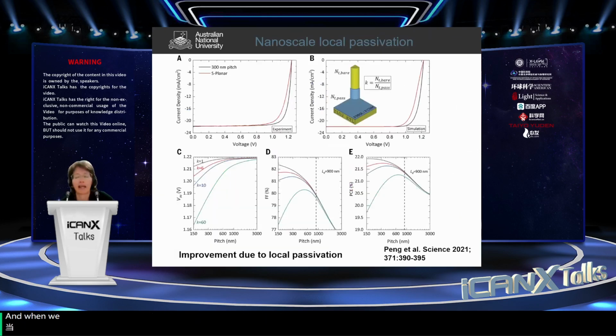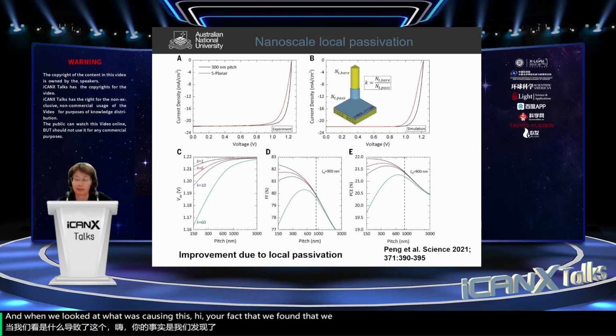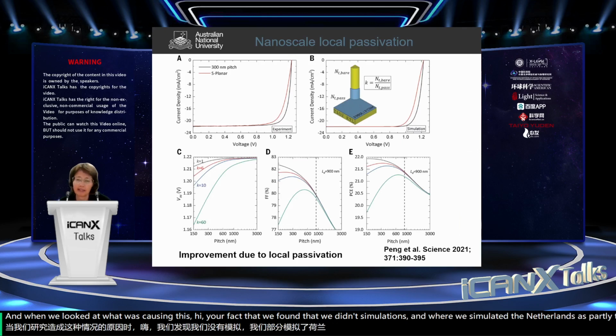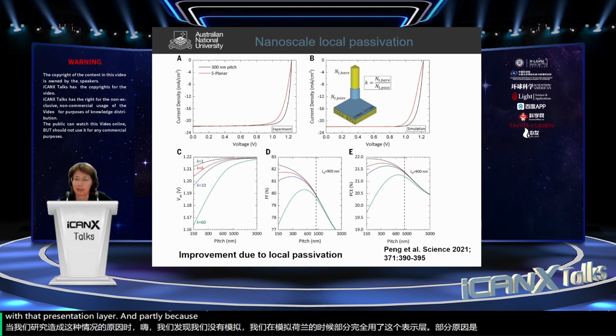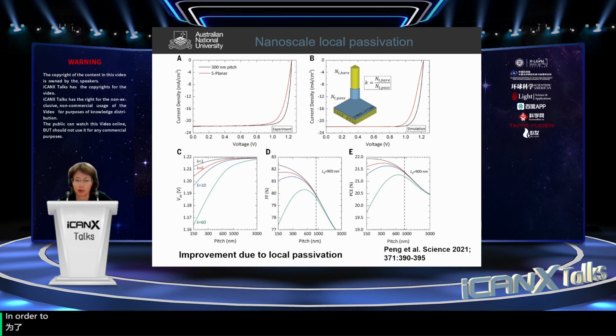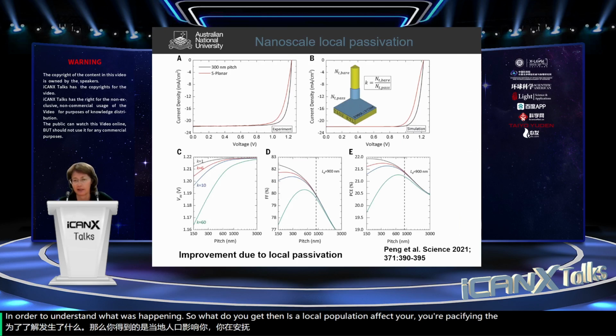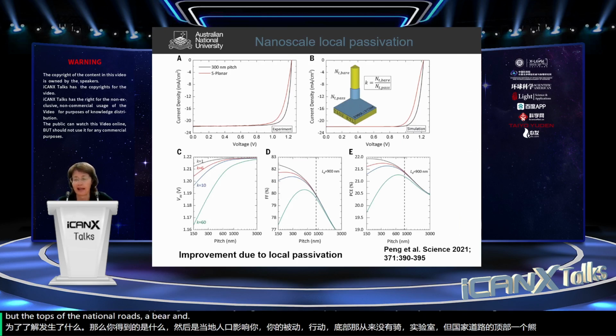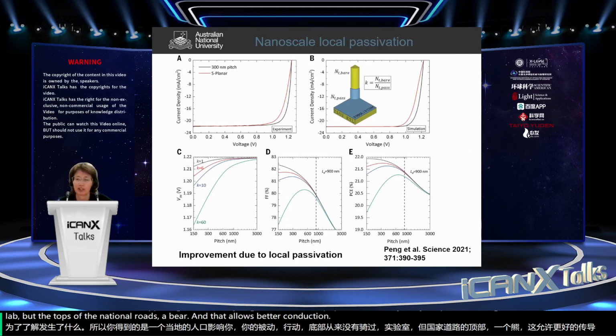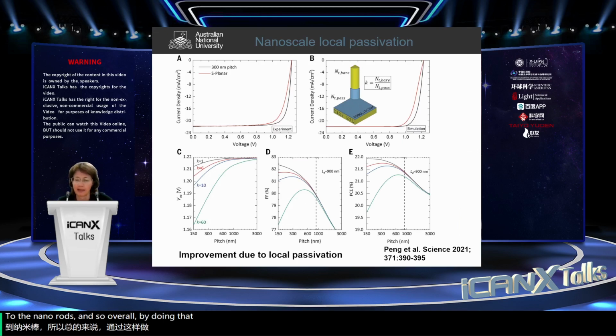When we looked at what was causing this high fill factor, we did some simulations where we simulated the nanorods as partly coated with the passivation layer and partly bare. We found that we needed to do that in order to understand what was happening. What you get then is a local passivation effect. You're passivating the bottom of that nanorod layer, but the tops of the nanorods are bare, and that allows better conduction to the nanorods. And so overall, you're able to get a higher fill factor.